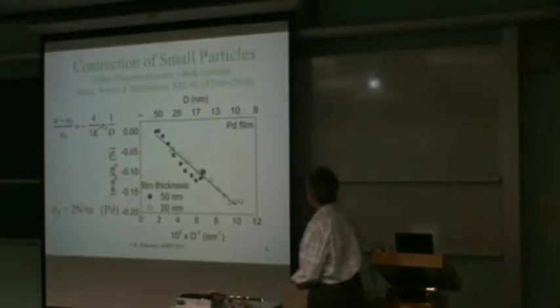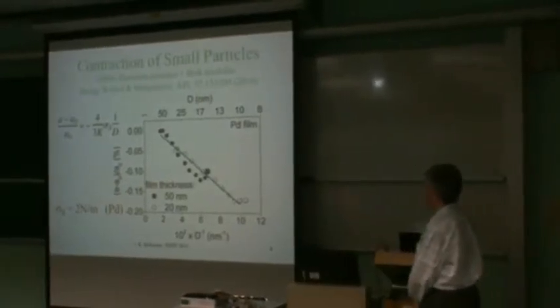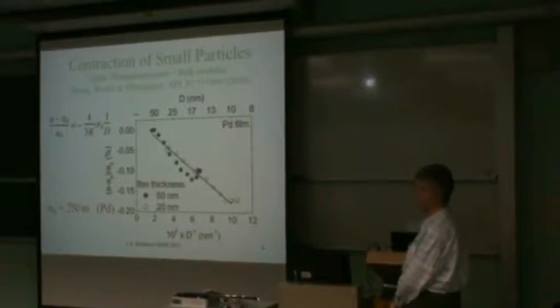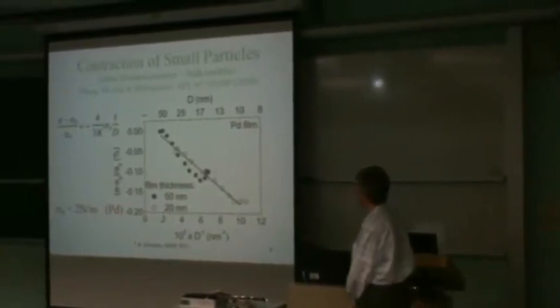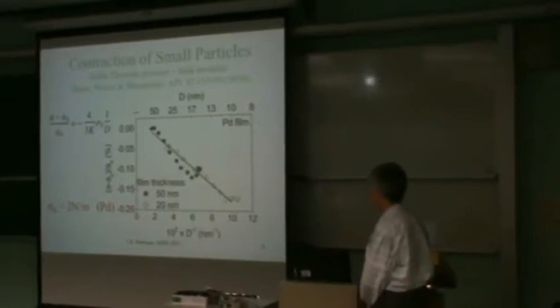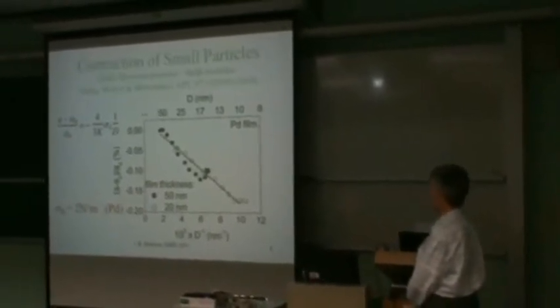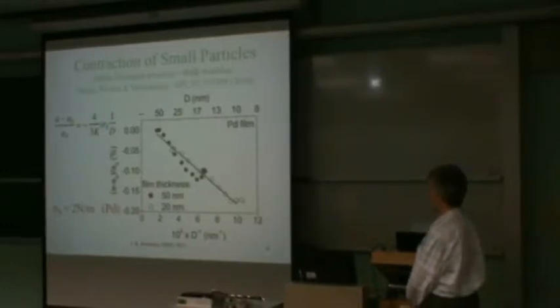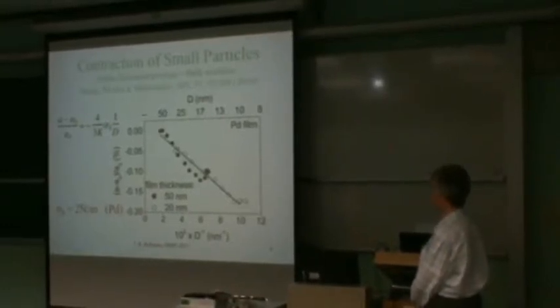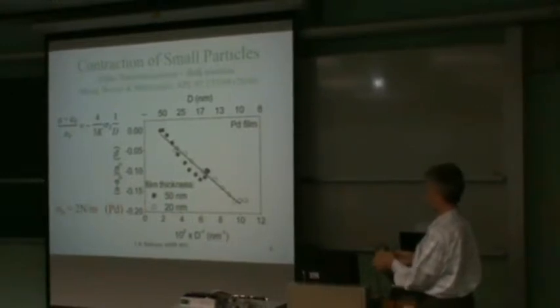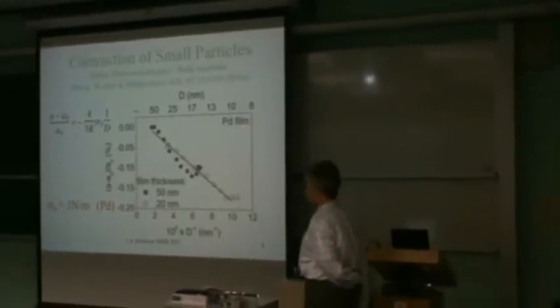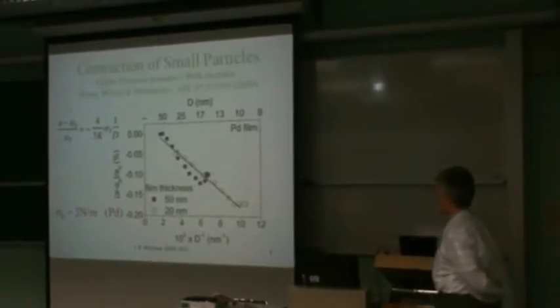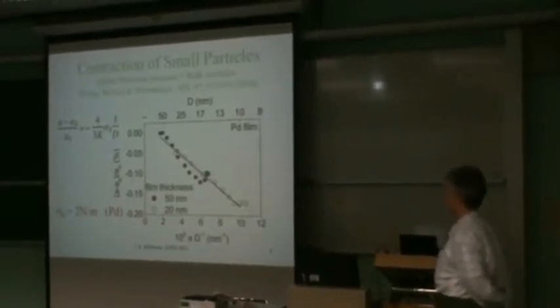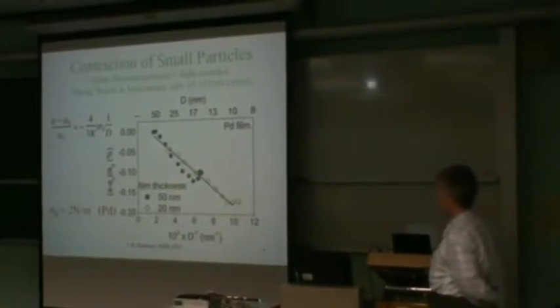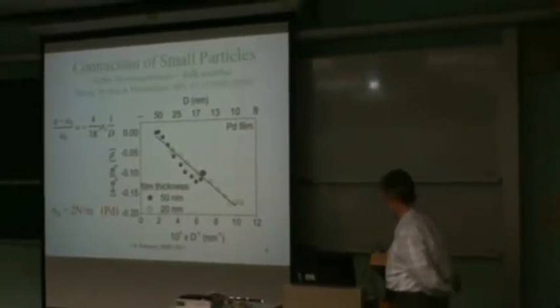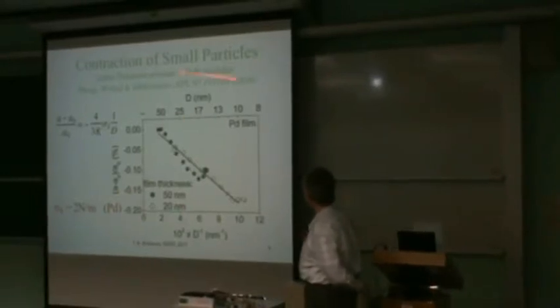Okay. So what I'll discuss before I show the coherent diffraction method itself is the kind of things that one would expect to see changing as you make the devices smaller and smaller. And the first thing that will change is that because a small structure of silicon will have more surface area, there will be a renormalization just of its lattice constant that will come about just due to the fact that there are surfaces present.